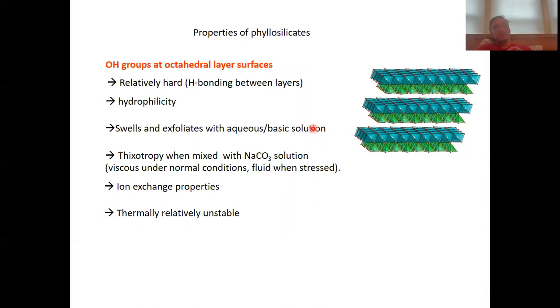You can intercalate metal ions, for example sodium, in between these layers, and then these layers exfoliate. So they are kind of going in solution, but now there are large structures in solution. Therefore, these solutions tend to be quite viscous, and they even show thixotropy. They behave kind of like ketchup. They flow very slowly until, like ketchup, when you exert mechanical force, they all of a sudden flow very quickly.